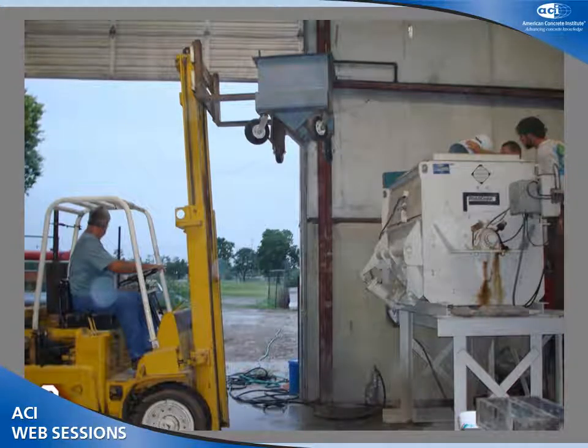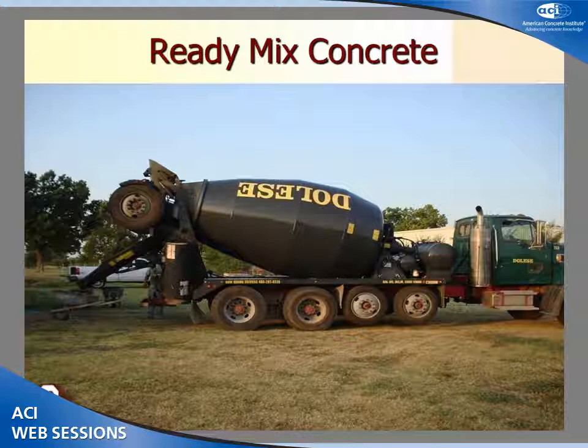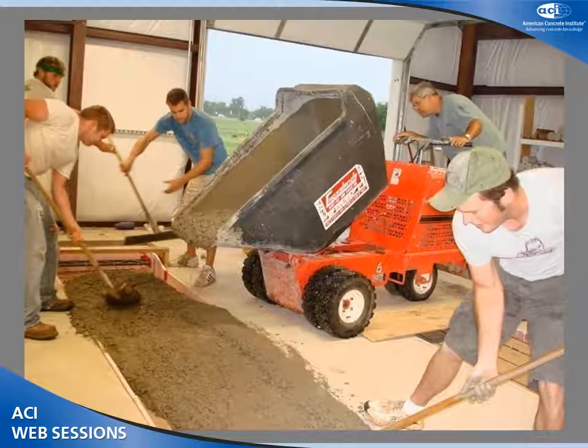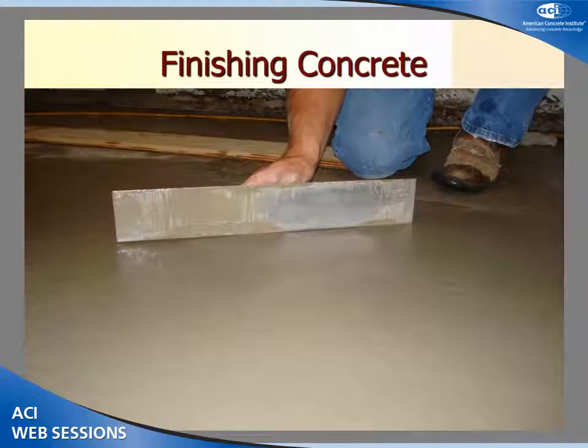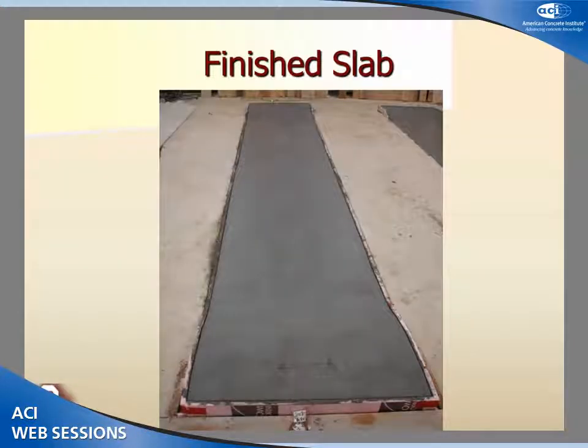Three of the mixes were batched at the University of Oklahoma's facility at Fears Lab, and we used ready-mix concrete from the Dolese company for four of our slab specimens. Here is a picture showing pouring the concrete into the slab bed. After pouring, the finishing crew finished the top surface of the concrete, and here are the finished slabs after all the work we've done.